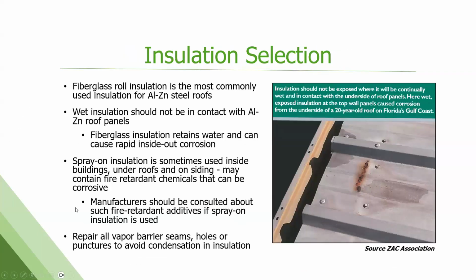Insulation. Fiberglass roll insulation is most commonly used, and it's fine, but if that's allowed to get wet some way, and now that wet insulation is sitting up against the back side of these panels, again, you will have accelerated corrosion that occurs from the inside out. Spray-on insulation is also sometimes used under roofs and siding. The only cautionary tale there is make sure it doesn't have a copper-containing fire retardant chemical in it, but there's plenty of products that are suitable. But again, the manufacturer of the panels should have guidelines and bulletins for all of this.